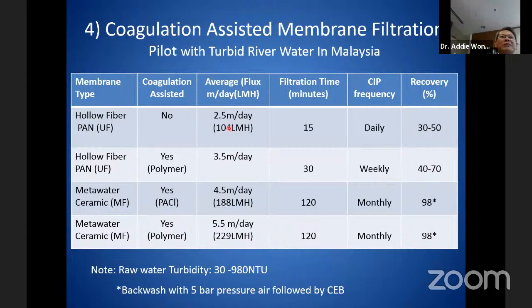When we put some polymer into the system, for the hollow fiber membrane, you don't do that, because this will blind it. In those days we didn't know, we thought this would be very good, but we generated a non-scheduled waste. The flux will increase from 2.5 to 3.5 meters per day. Sorry, I forgot to put in the conversion, but you can see the increase. The filtration time can be lengthened to 30 minutes, CIP only needs to be done once a week, and recovery is much higher compared to before.